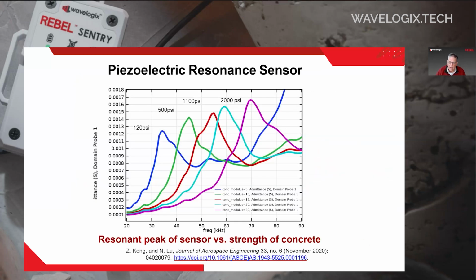And if we look at concrete as it's curing and as it gets stiffer, and we look at that resonant frequency, we're going to see it shift from the left to the right. And you can see in the graph the corresponding compressive strength: 120 psi, 500, 1100, 2000 psi. We have a very unique way of using a non-destructive test in real time that gives us accurate compressive strength as that concrete cures. And that, in essence, is the basis of our product and how it works.